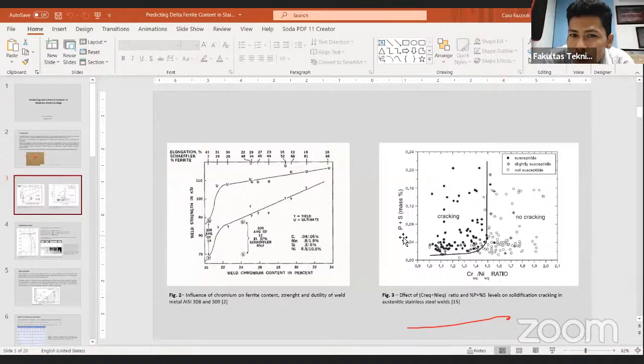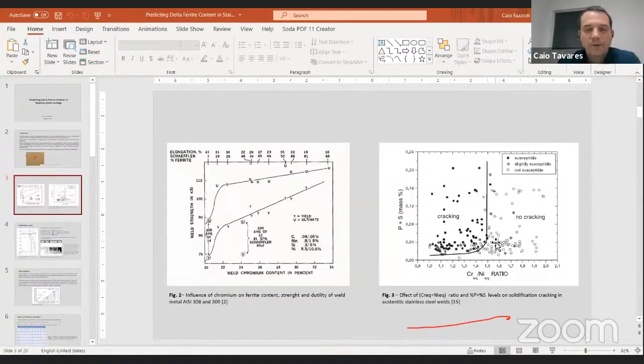So you mean that, by the presence of the delta ferrite, the phosphorus and sulfur, which usually precipitate on the grain boundary of the austenite, if there is a significant amount of delta ferrite, this precipitation can be avoided. Yes, it can be avoided. And this is not a significant amount. We are talking about like 4%, between 4 and 8%. Okay. Not too much, but it's important to have some delta ferrite in stainless steels for some applications, to avoid these kinds of issues.